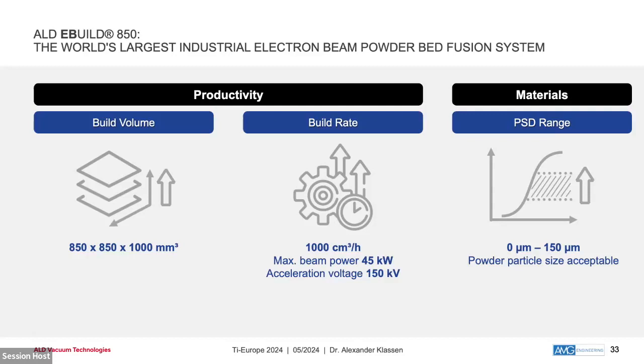So we are not confined to the typical powder particle size ranges, like for laser beam melting between 20 to 40 microns, or electron beam melting, which is usually found between 40 or 50 to 100 microns. And this makes it economically viable to open up a whole new field of applications. One of those I will show you in a couple of slides. First,